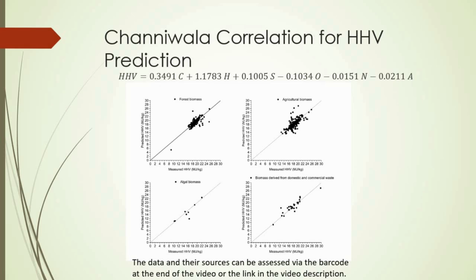A general positive correlation exists between predicted and measured values, indicating the model captures the overall trend. For forest biomass, data points cluster closely around the 1-to-1 line, suggesting high accuracy, though a few outliers are present. Agricultural biomass follows a similar pattern, with strong alignment to the 1-to-1 line. Algal biomass has fewer data points but still correlates reasonably well. Domestic and commercial waste biomass shows more scattered data, but the trend still follows the 1-to-1 line.